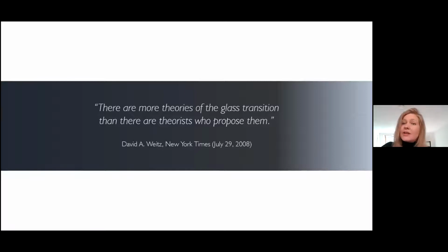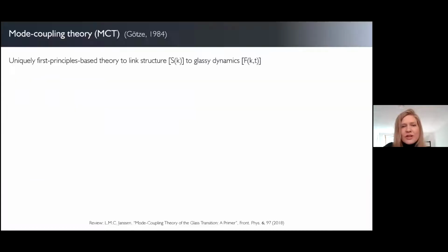All right, now actually there is already a first principles theory of the glass transition. It's called Mode-Coupling Theory, developed by Wolfgang Goetze and co-workers in the early 80s. And this theory still stands out as the unique first principles based framework for the glass transition, where it tries to link the small structural changes as encoded in the static structure factor to the emergence of glassy dynamics as encoded in this intermediate scattering function. Now, I'll briefly walk you through the theory because it will become important later on.